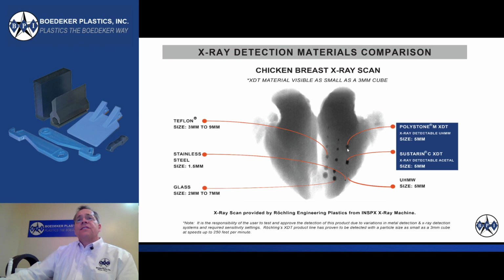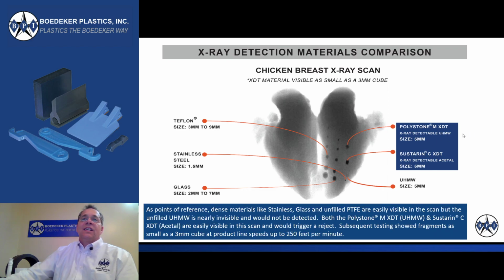Now, by contrast, here are your 2 X-ray detectable plastics. Again, the Polystone M XDT, the metal or X-ray detectable ultra high molecular weight polyethylene, and the Sustarin C XDT, the X-ray detectable acetal. And both of those are 5 millimeters in size and very easy to see in contrast.